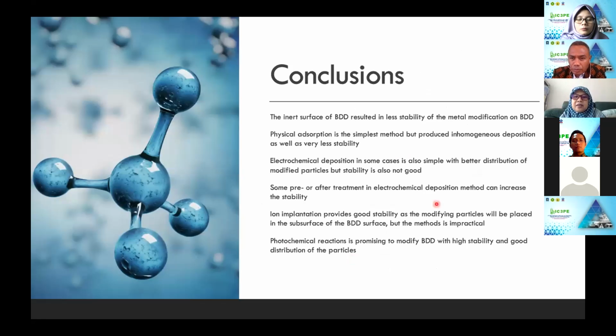And as the conclusion, the inert surface of BDD resulted in less stability of the metal modification of boron doped diamond, and physical adsorption is the simplest method, but produces inhomogeneous deposition and also less stability. Electrochemical deposition will be better for distribution, but stability is also not good. Some pre or post treatment in electrochemical deposition can increase the stability. Ion implantation provides good stability, but the method is impractical because not everybody can provide the accelerator. Photochemical reaction will be promising with good stability and good distribution of the particles.